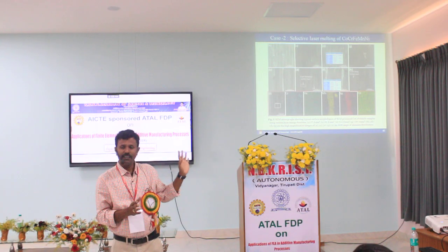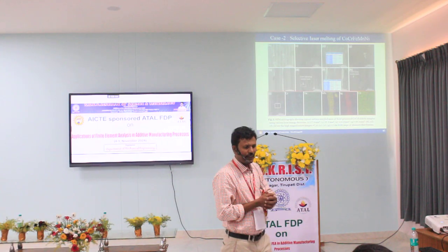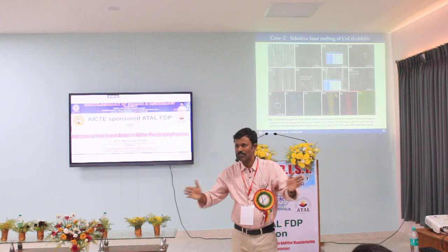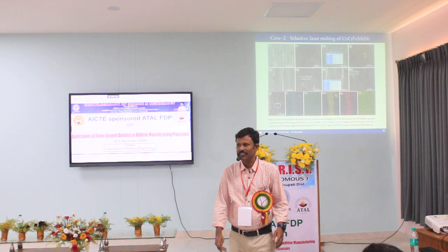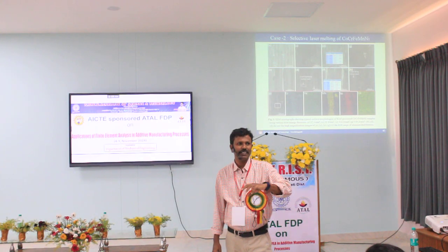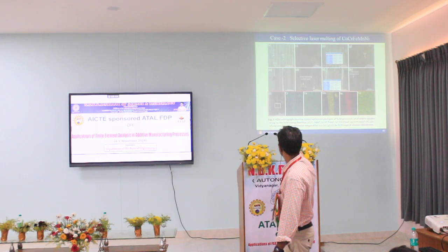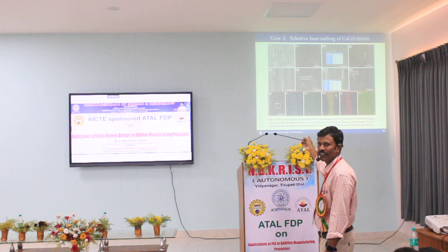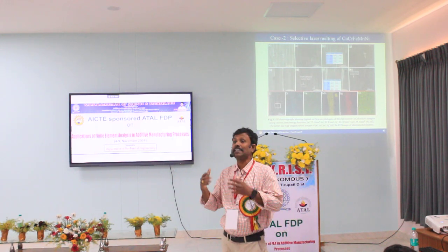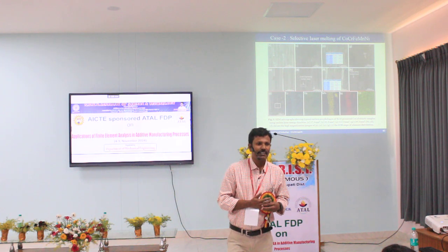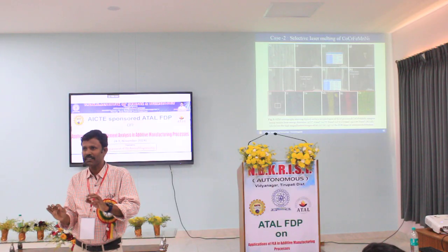Especially when doing selective laser melting, we felt that along the complete channel, the elements used to separate. That is the reason everything can crack. Even after optimizing and getting a physically defect-free system, metallurgical defects used to stay. When we analyzed these, we realized that they are a detrimental phase. That means in application, when you use it, it will fail.